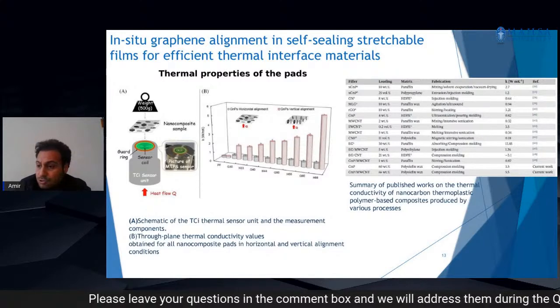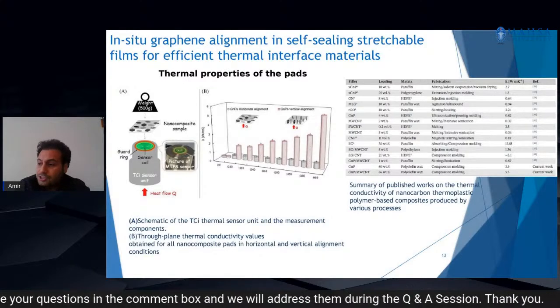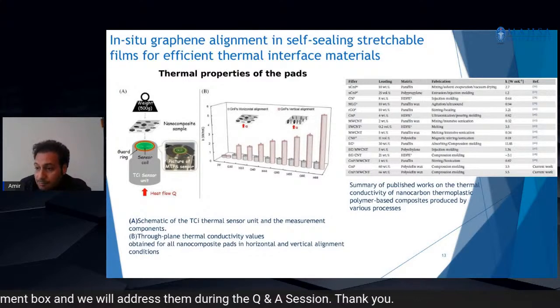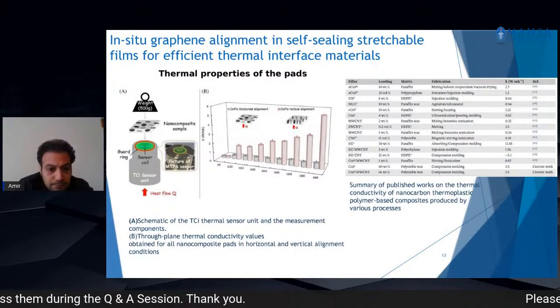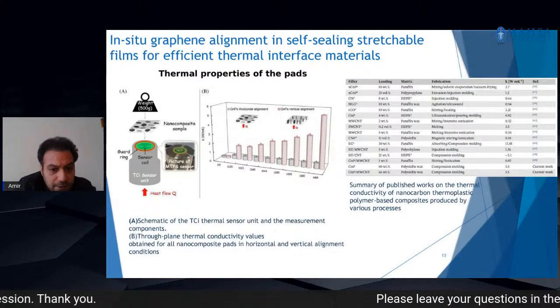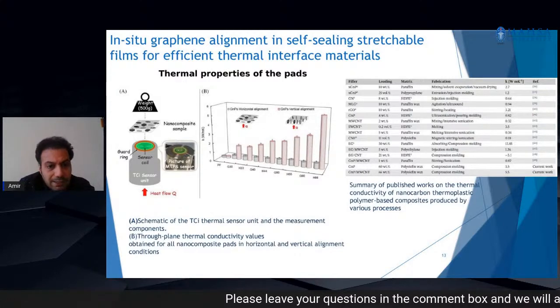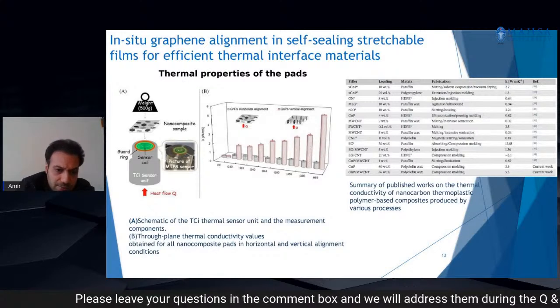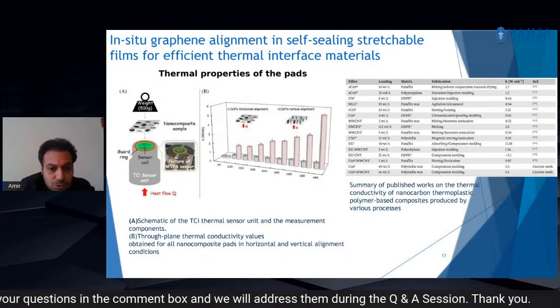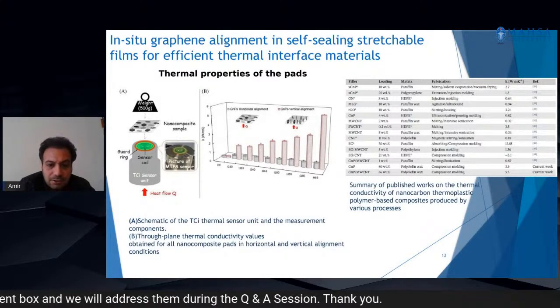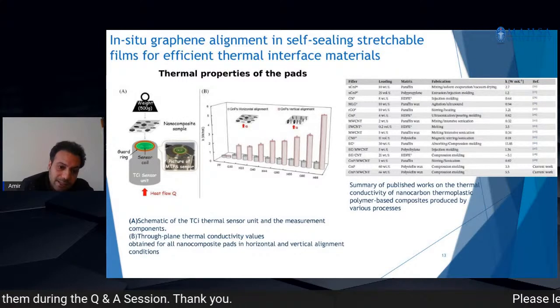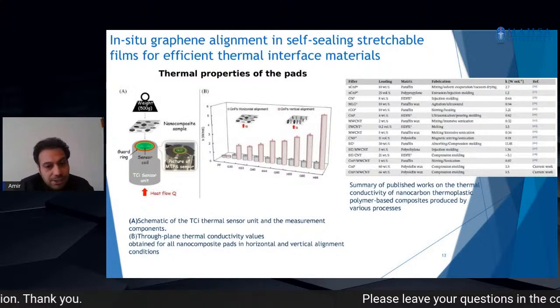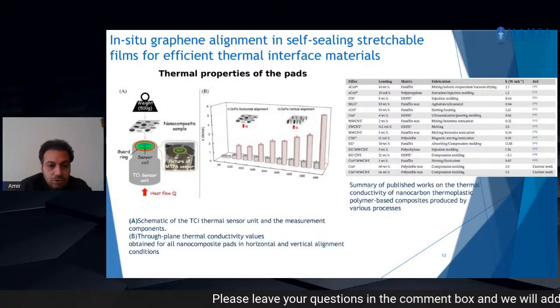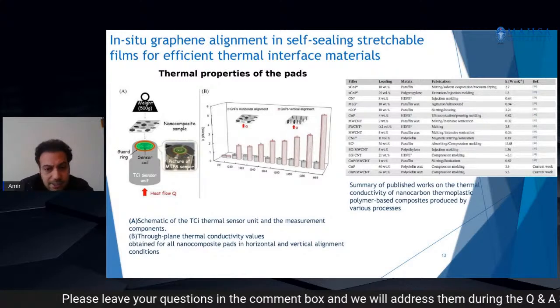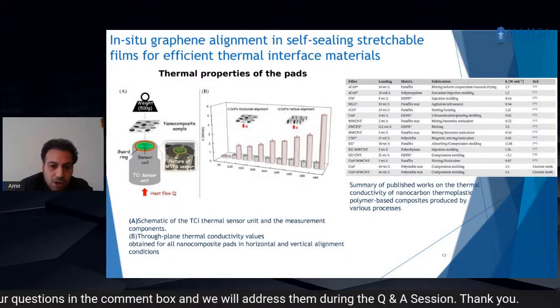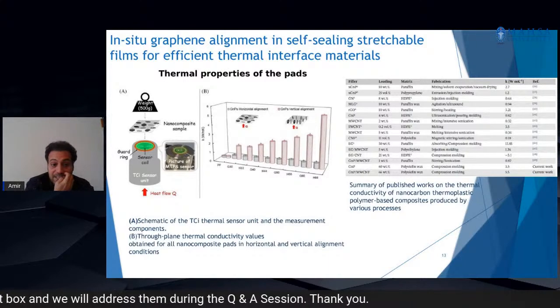The plot in the middle of the screen shows the through-plane thermal conductivity measurement of all nanocomposite samples. In the sensor, we put our sample and measure the thermal conductivity with our TCI system. You can see that we are comparing the differences between the aligned sample, where we oriented the fillers of each sample, and the bulk one. You can see big differences when we compare with the aligned sample.